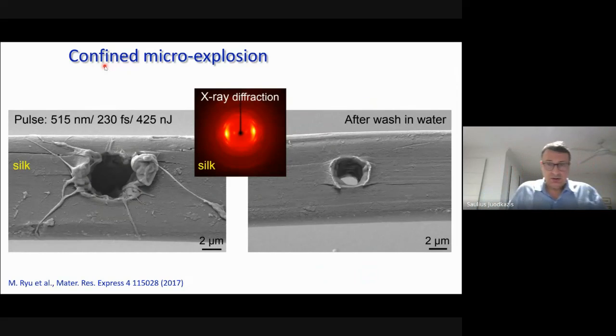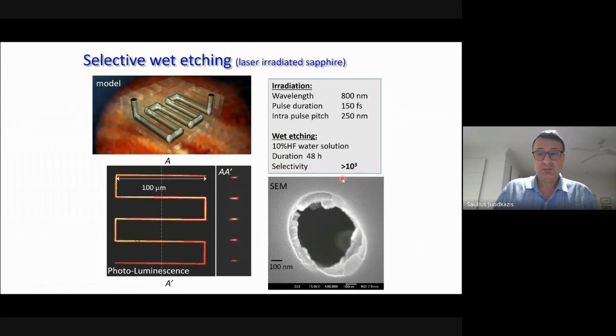Just to finish these exotic energy deposition scenarios, let's have a look at silk. This is a biocrystal. You see it from X-ray diffraction. There are very clear diffraction bands. So it's 85% crystalline material. A single femtosecond pulse at green wavelengths, which is transparent for silk, is making this strong damage. You can recognize those features here, and this is actually amorphous silk, which again does not exist if you don't quench silk at 10 to the power 5 Kelvin per second. So it should be very fast thermal quenching to recover amorphous silk. And that amorphous silk has an interesting feature. You can wash it out in water. Silk is not dissolved in water, but that amorphous silk is washed out. So washing out of modified areas can be a practical tool.